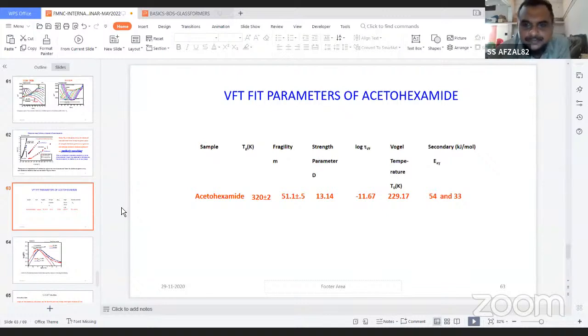From this, we can understand that there are two relaxations in the glassy state, and the fragility corresponds to the strength of the glassy state. That is, whether the glassy state is fragile or strong. So the value of 51 corresponds to intermediate fragile, and the glass transition temperature is 320 Kelvin. That is above the room temperature. Which means the higher the value of glass transition temperature, the more stable it is. So these are the most important values of the conclusion.